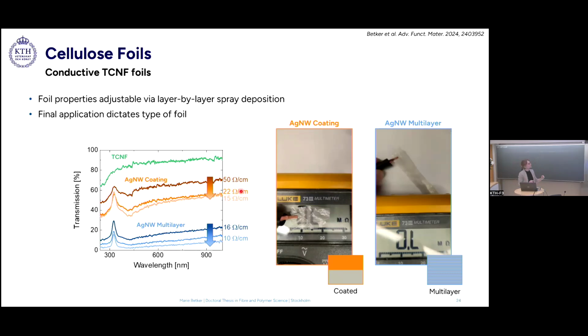But when we now go to the mixed type, which is the blue one, we can see this foil is not so transparent anymore, but it's highly conductive. And you can see the values are very stable. So in the end, your final application dictates what kind of foil you would use.